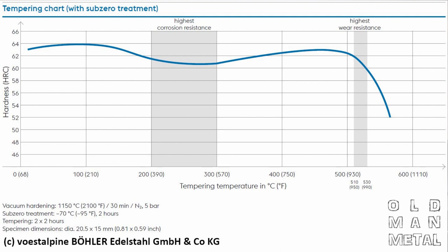The tempering then depends on whether you want optimal corrosion resistance or optimal wear resistance, and in both cases there's an initial sub-zero treatment to transform any remaining austenite that survived the quench, and that initial treatment involves holding the pre-cooled steel at minus 95 degrees for 2 hours. After that, the steel is heated slowly to the tempering temperature and held for at least 2 hours, more if it's a thicker working piece. And the tempering temperature should be between 390 and 570 if you want optimal corrosion resistance, or it should be between 950 and 990 for optimal wear resistance. So you sort of have to pick which of those two you want to get the best of. And both of those scenarios actually require two identical tempering steps. You don't do the tempering once, you have to do it twice.